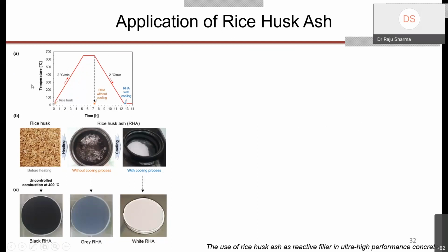But what they do is they get a rice husk ash over here, right? So black RHA means uncontrolled combustion. This is RHA basically at 400 degrees Celsius, an RHA without cooling. So they just take the RHA out from the furnace after this particular burning. And then in the next phase, they allow the RHA to cool down, and they take out that particular material at 13 hours, right?